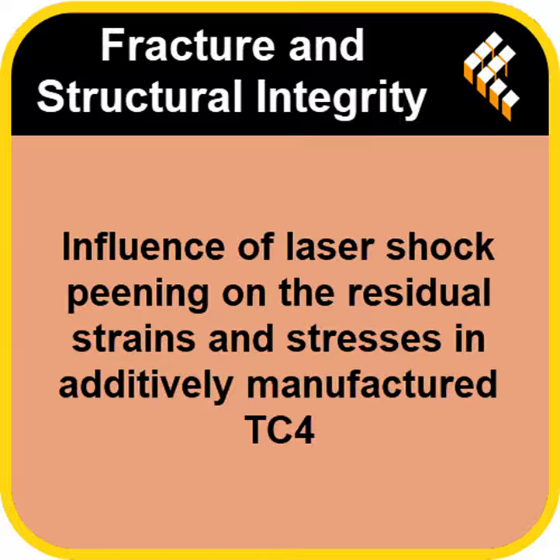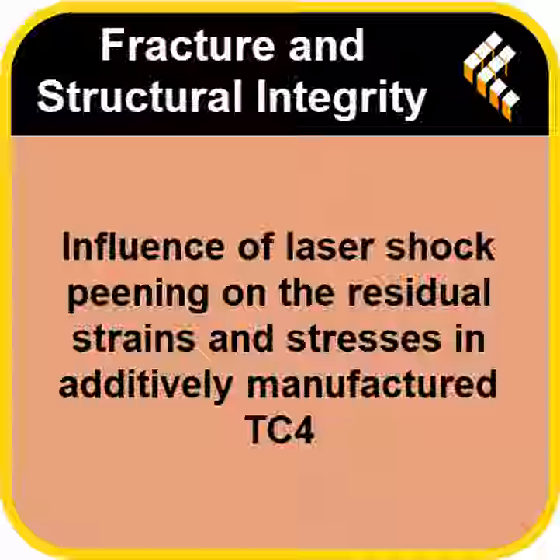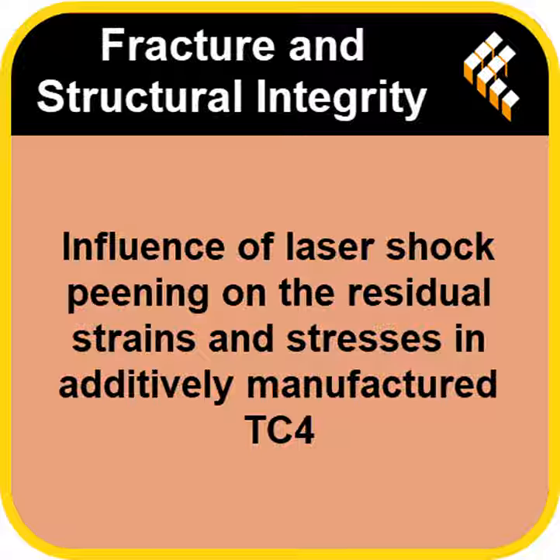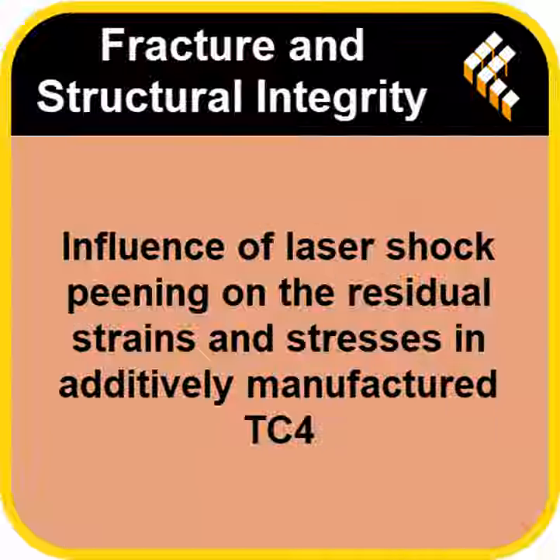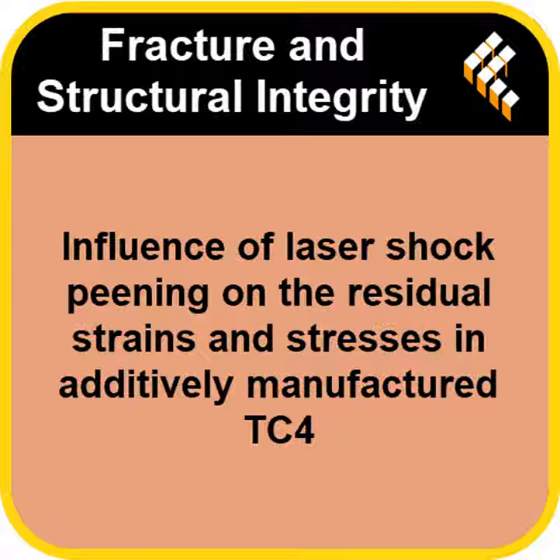Got it, the absorber. Then you cover that absorber with a clear liquid, usually just water, that acts as a confining layer. Okay, water on top. Now the high-power laser pulse shoots through the water and bam, hits the absorber layer. Instant vaporization, I assume. Instantly, the absorber turns into a superheated high-pressure plasma. But here's the key. It's trapped. The water layer acts like a lid, confining that rapidly expanding plasma. So the water isn't just for cooling, it's actively focusing the pressure. Precisely. It forces the plasma expansion to generate this incredibly intense pressure wave. We're talking units to tens of gigapascals. Gigapascals. That's immense pressure, crushing force. It is. And this pressure wave travels into the titanium as a shock wave. If that pressure is higher than the titanium's dynamic yield strength, its resistance to sudden force.